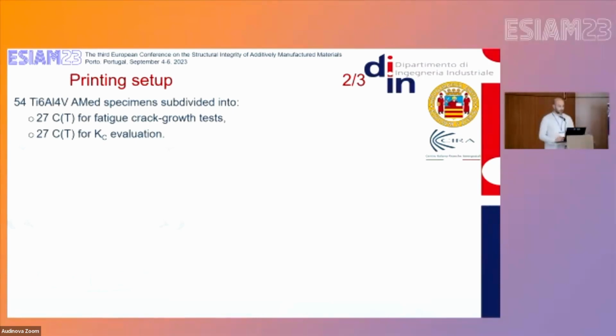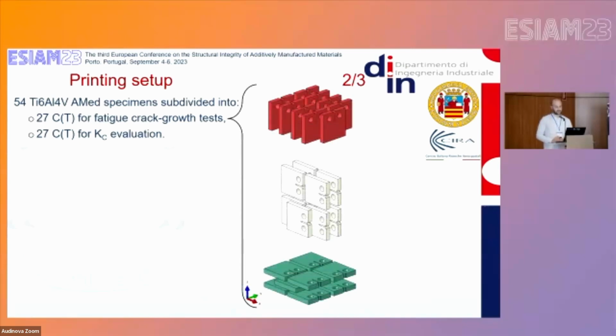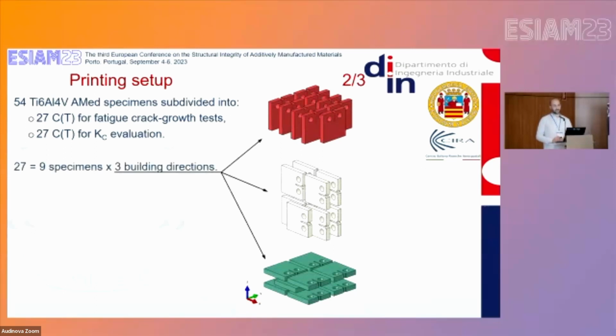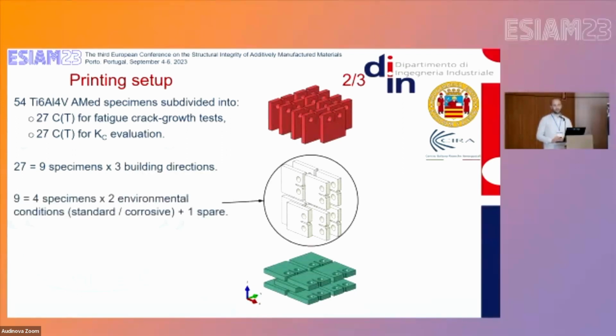So from the manufacturing, we prepared a total of 54 samples that we equally subdivided into 27 samples for the fatigue crack growth tests and 27 samples for the quasi-static tests, so for evaluating the K-critical. Looking at the fatigue crack growth tests, these were 27 subdivided into 3 building directions, so 9 specimens per each of the 3 building directions. And they were 9 because of 4 specimens that were tested in air condition, in laboratory condition in air. 4 specimens were tested in a corrosive environment, and 1 was a spare specimen that was used for the calibration of the machine.